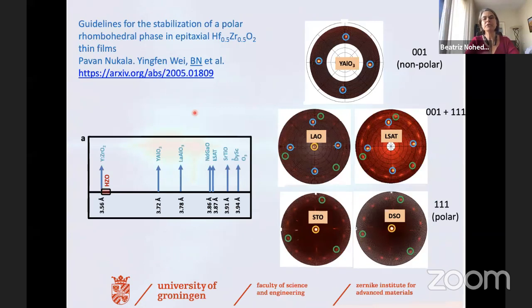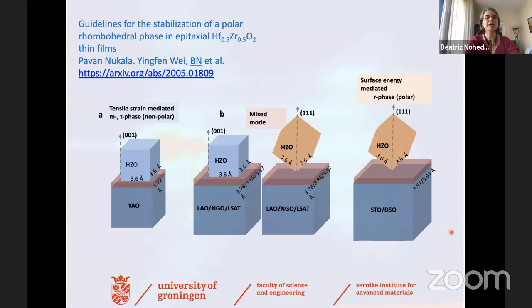So by now we have very good control on these materials, and in this paper you can see that there are certain guidelines that can help you to stabilize the rhombohedral phase on different substrates. And we have seen that you need a certain amount of strain if you want to have a pure 111 polar phase oriented. In particular, if grown under tensile strain, there is a tendency to stabilize the monoclinic or the tetragonal nonpolar phases, while in materials with more compressive strain,